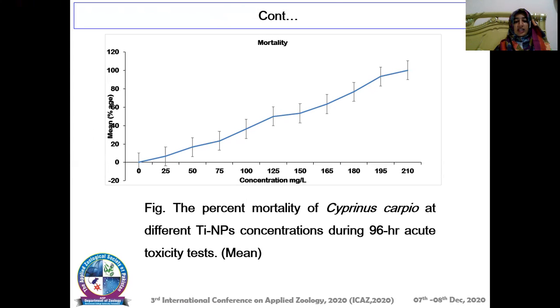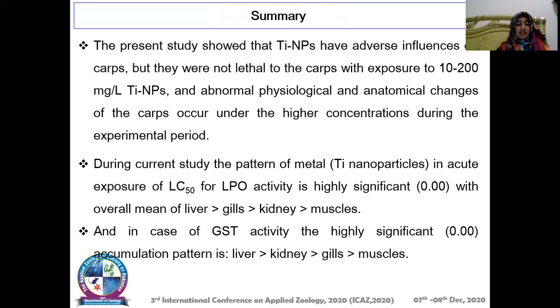Here I want to show the mortality rate of the fish Cyprinus carpio at different titanium nanoparticles concentrations during the 96-hour acute toxicity test. The final results that I concluded: the pattern of titanium nanoparticles for lipid peroxidation activity at 96-hour concentration and lethal concentration was recorded as follows. Liver showed maximum disabilities as compared to gills, kidney, and muscles.